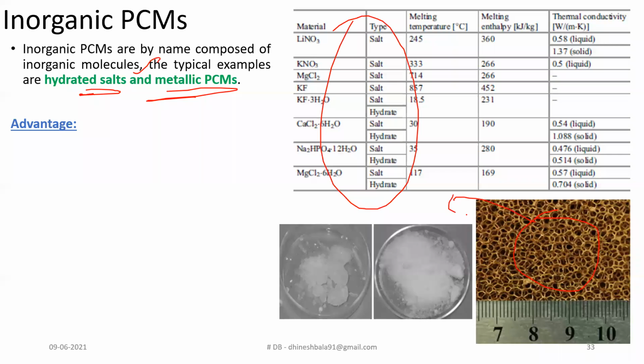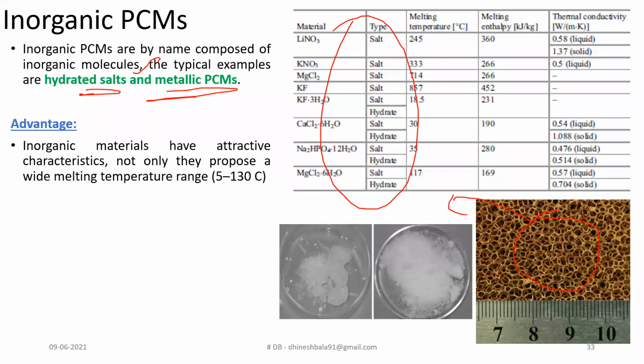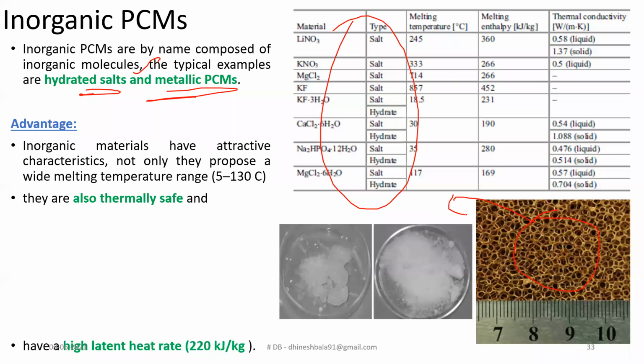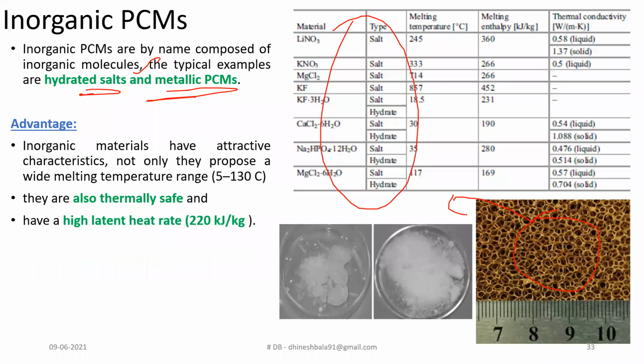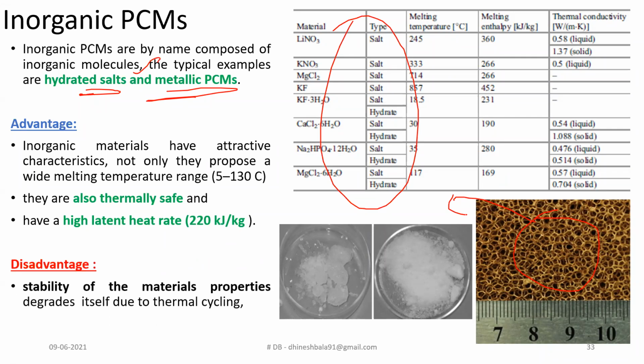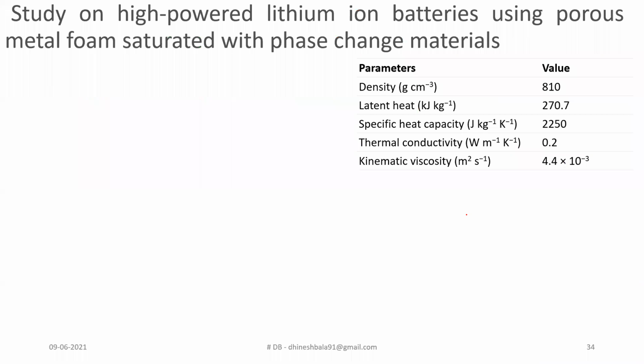So one of the key disadvantages of these inorganic PCMs: inorganic materials have attractive characteristics, not only a wide melting temperature range, and also they are thermally safe as compared to the organic phase change material. And it has a high heat rate, and the disadvantage is the stability of the material would start to degrade based on the thermal cycling. So you'll be adding heat and removing it. Because of this, the material properties would get varied. So now we'll try to understand this with one interesting particular study.